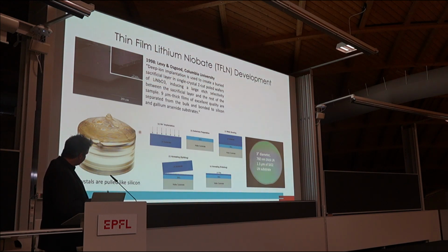We take the lithium niobate, it's grown in the Czochralski process, similar to silicon. We cut it in wafers like salami, then you come in and implant some ions, okay? And then these ions actually damage a layer of lithium niobate below the surface.